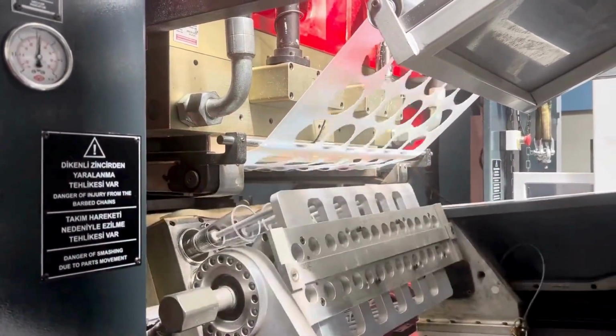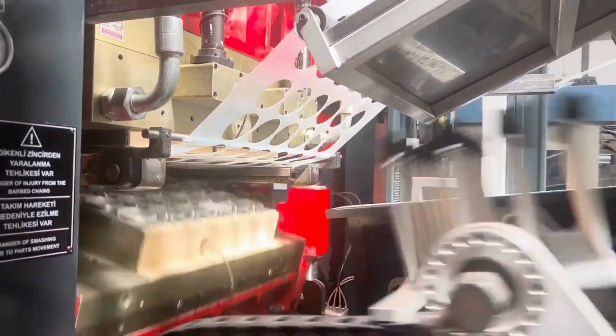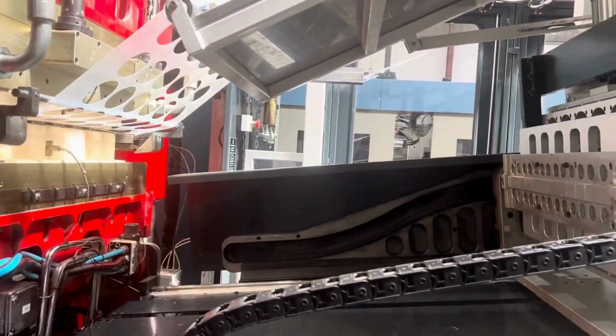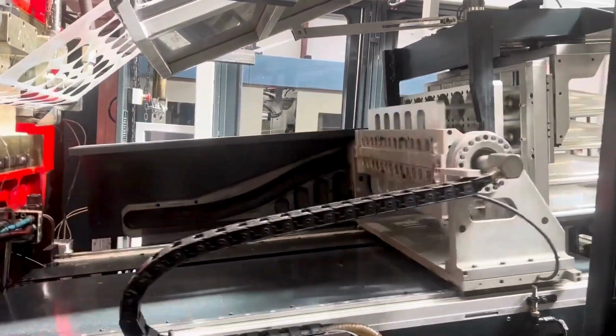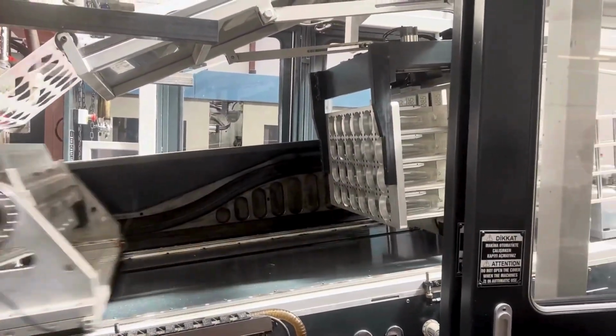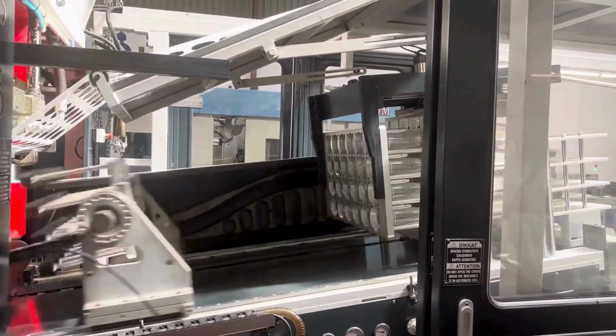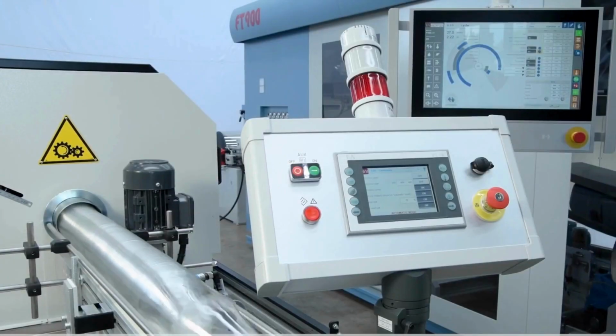The next major step is rim rolling, which gives each cup its smooth, rounded edge. First, the rim is preheated, a step called thermal conditioning. The edge is warmed to just below the polymer's glass transition temperature, TG, where the material shifts from a stiff, glassy solid to a more flexible, viscoelastic state.